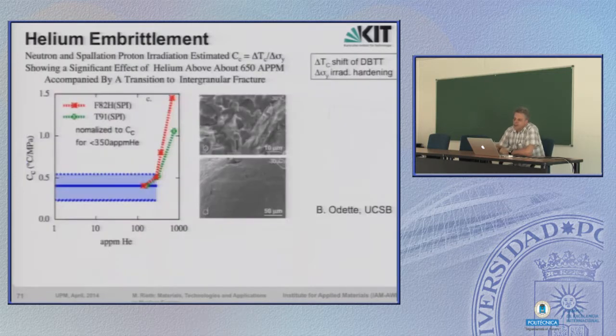There are also models, of course. We don't have to go into detail here, but one of these studies is very interesting. They predict that the helium effect is more or less negligible up to about, well, they say 650 ppm helium in 9 chromium steel. In terms of practical measure, let's say a few 100 ppm helium is what a steel can sustain, and then there is a sudden drop of all the mechanical properties in terms of embrittlement.